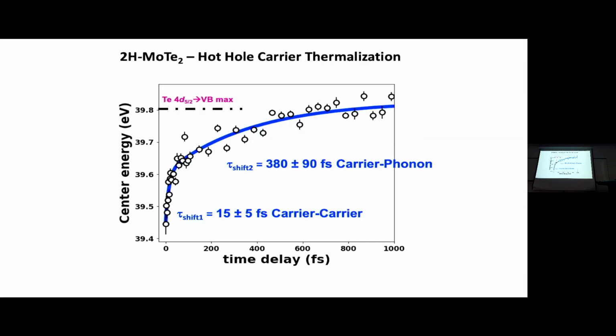But let's just take one example. Suppose I want to follow the hot holes, and I want to figure out what is the time scale. Well, it turns out if I pick a region and measure carefully, I can see this shift here of the center energy of this hot hole distribution. And there's a very fast part. It's 15 plus or minus 5 femtoseconds. And there's a slower part, which is around 380 plus or minus 90 femtoseconds. And we can assign the fast part to the carrier-carrier scattering. So it's like a rapid thermalization.